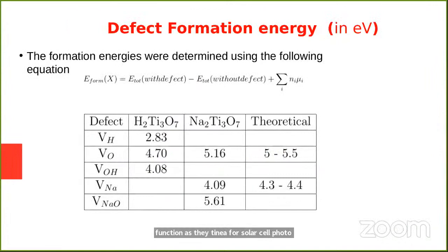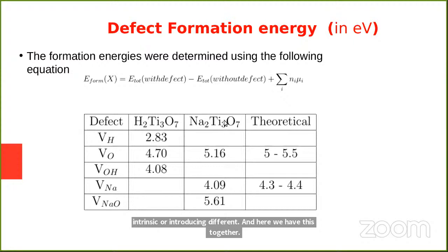photocatalysts. And after that, we introduce a defect. The electronic and optical properties of oxides are often determined by the presence of defects, either intrinsic or introduced. And here we have investigated the defects of hydrogen titanate and sodium titanate, including hydrogen vacancy, sodium vacancy, OH vacancy, and sodium oxide vacancy. And we compare with other theoretical work.